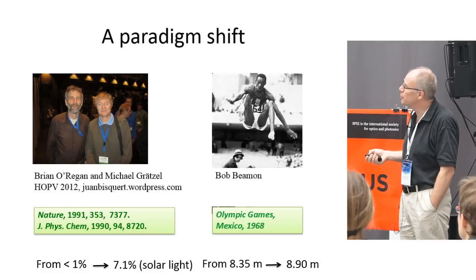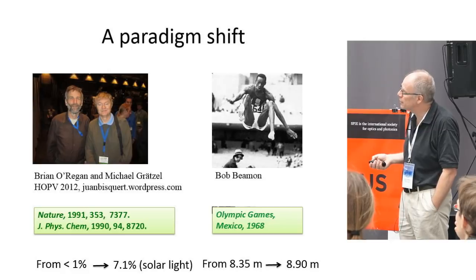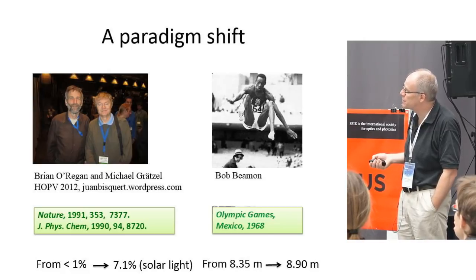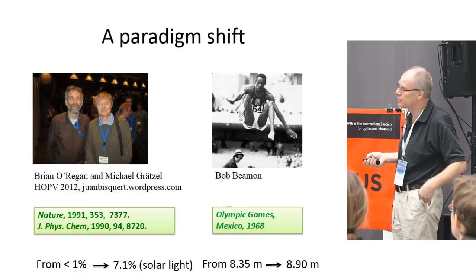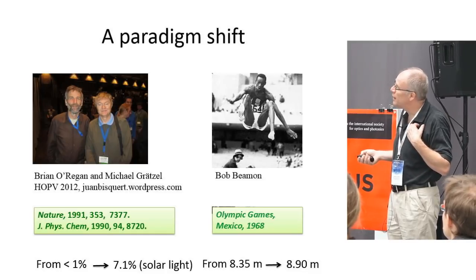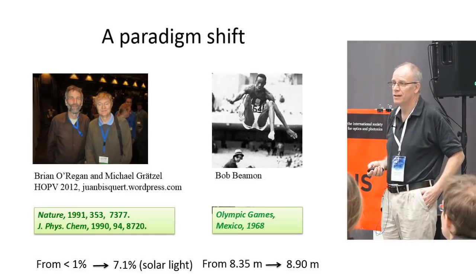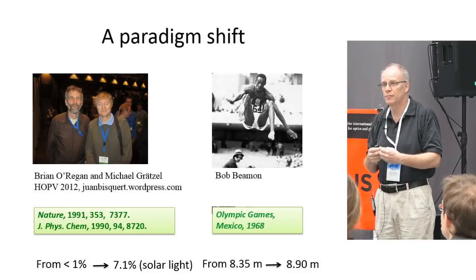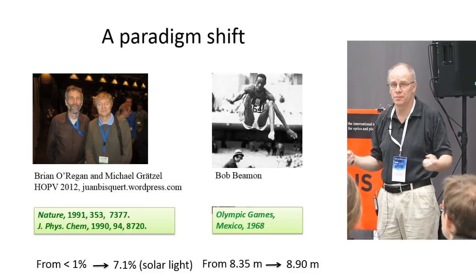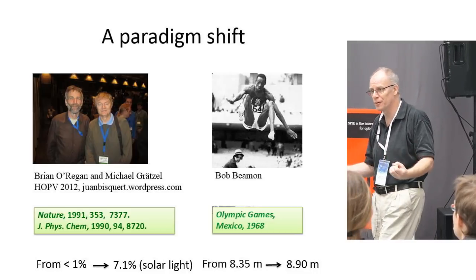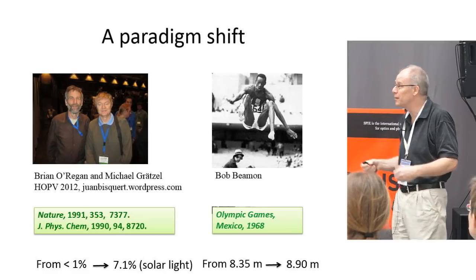But they made in one go, efficiency came up from much less than 1% in sunlight to 7%, an order of magnitude increase. And the most interesting thing was that it was based on a way of doing solar cell which you shouldn't do. It shouldn't theoretically work. So it was very exciting, of course, how can it work?